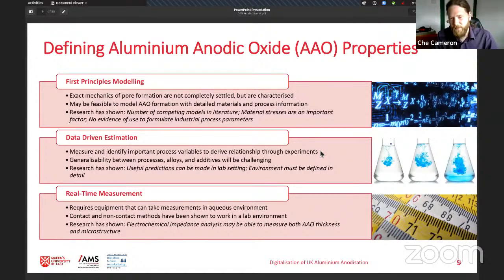A level up from that is data-driven techniques, where essentially what you do is take a controlled environment and undertake anodization in that and measure all the different variables that you're changing and derive a relationship to work out what thickness the layer will be, what the pores will be like. This has shown useful predictions in lab settings and very controlled settings. Quite good models have come out of that, but there are issues generalizing across different processes, different alloys, different additives, and in the practical terms of industry, different tank sizes, shapes, part geometries.